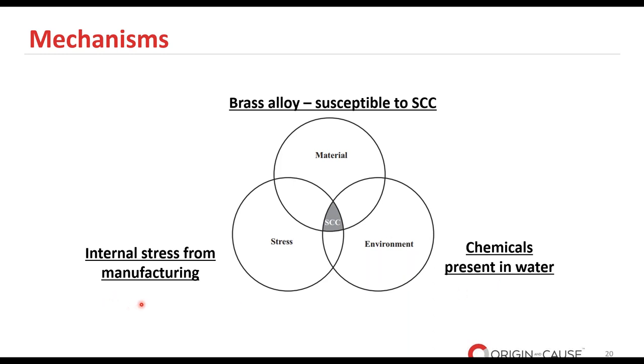And lastly here, we can't overlook the influence of manufacturing practices. The presence of internal stresses from manufacturing further predisposes the material to cracking. Without proper stress relief post-manufacture, these internal stresses can act as catalysts for SCC when combined with the environmental factors. So really, a trifecta of mechanisms, so to speak: material properties, environmental influences, manufacturing residual stresses, they all collaboratively increase the risk of stress corrosion cracking in this context.